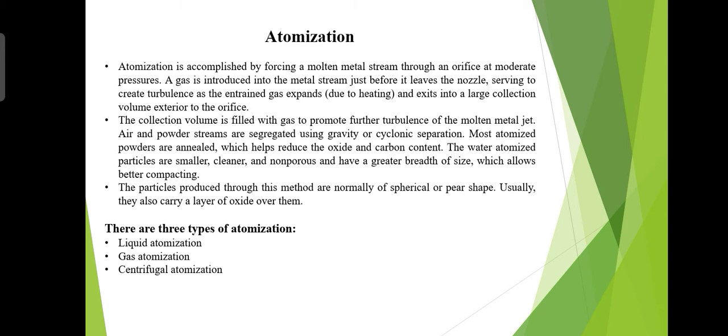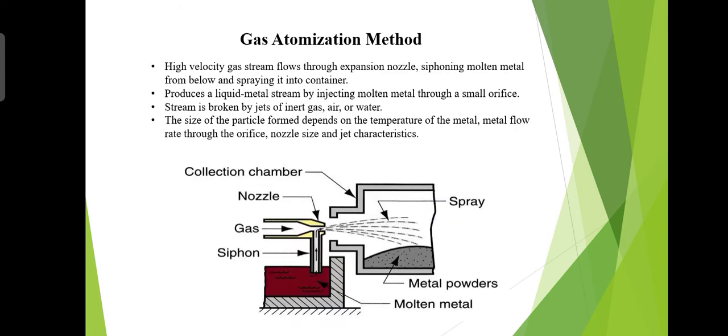To accomplish this, the melt stock in the form of elemental multiple and multi-element metallic alloys and or high quality scrap is melted in an induction arc or other type of furnace. After the bath is molten and homogeneous, it is transferred to the tundish, which is a reservoir used to supply a constant controlled flow of metal into the atomization chamber. As the metal stream exits the tundish, and this is the gas atomization method,